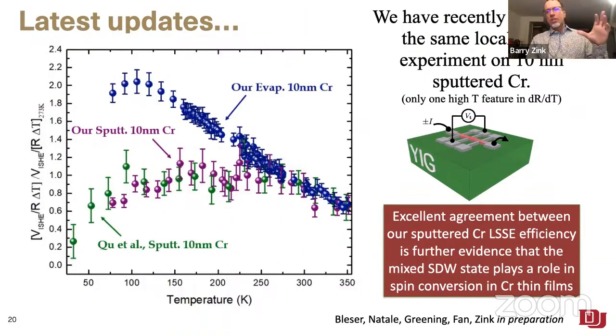Okay, this is the latest update. That was all comparing just to other people's sputtered chromium. We did the exact same experiment that I described with this local spin heating on a sputtered chromium film recently. And you can see, I don't want to get too much into the details, but the purple dots are our data. The green dots are Chiling's data that I was just using for the original comparison. So very, very good agreement in the temperature dependence of the sputtered chromium films that we're getting in these experiments. So that's another nice confirmation that nothing's too crazy is happening in these experiments for us.